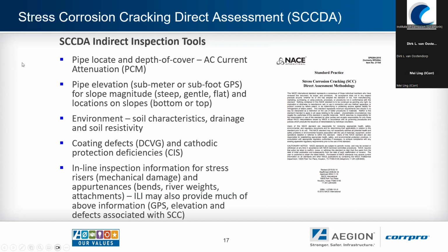Switching gears to stress corrosion cracking. This one has some other considerations that one has to take into play with for example, the location of the pipe, the depth of the pipe, the depth of cover. So for those pieces, we typically would use something like a pipeline current mapper to accumulate this data. The pipe elevation is a large part of that as well. So usually typically sub-meter data to get the geospatial alignment.